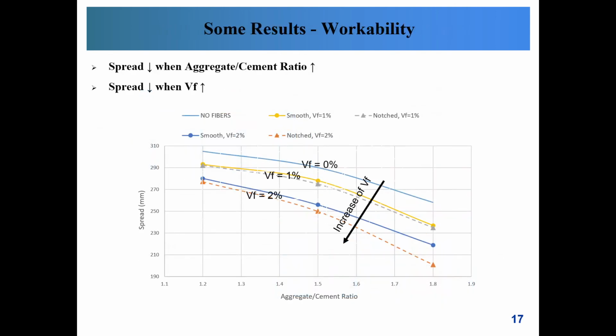Here you see the effect of adding more aggregates and fibers on the workability of the mix. As you can see, the spread decreases with the increase in aggregate-to-cement ratio. So the more aggregate you add, the more you lose workability. A similar trend is seen with the addition of fibers. The more fibers you add, here 0, 1 and 2 volume percent, the more you lose workability. The diagram is also an excellent indicator how changing the aggregate-to-cement ratio can be used to offset the effect of added fiber reinforcement.